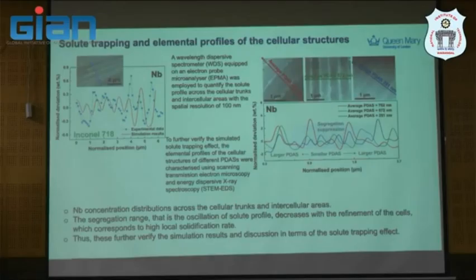That's why I said microsegregation is linked to dislocations. That is the next study, actually. The segregation length here is an oscillation of the solute profile, increased and decreased because of refinement of the cell structure during the high solidification rate. And this simulation result has been verified with experiment in terms of solute trapping. So we can approximately capture the effect. And what we do now is try to use this for particular cases.